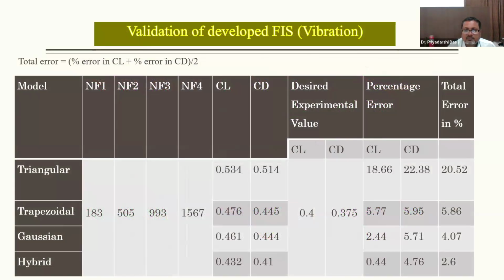This is the validation of the developed model with the experimental value, and the percentage of error we can find for the triangular membership function. Using the vibration data, the percentage of error is 20%. For trapezoidal, it is 5.8%. For Gaussian, it is 4.07%. And for hybrid, it is 2.6%. That means using the hybrid membership function effectively produces a close resemblance to the experimental value.